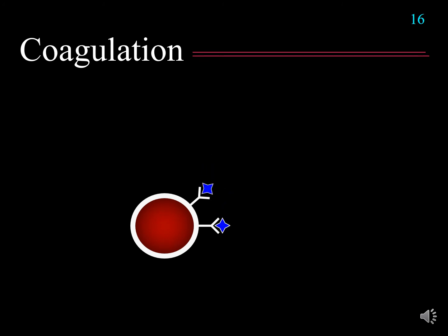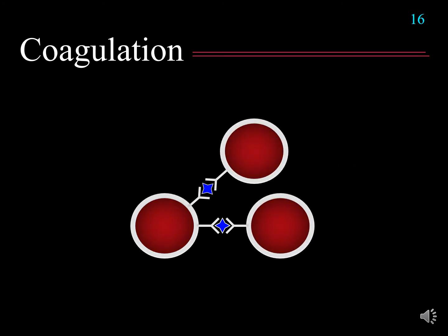So with the gold nanoparticle full of antibody on the surface, if you have the antigen in our analyte, then the antigen can attach to the antibody on the surface of the gold. And because we have so many gold nanoparticles here, the antigen initiates the coagulation or precipitation of the colloidal gold.